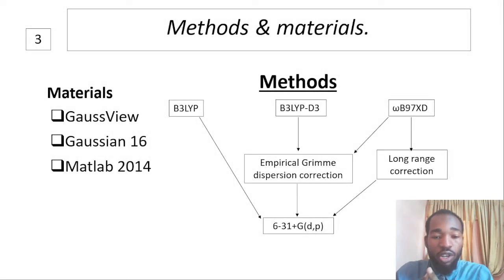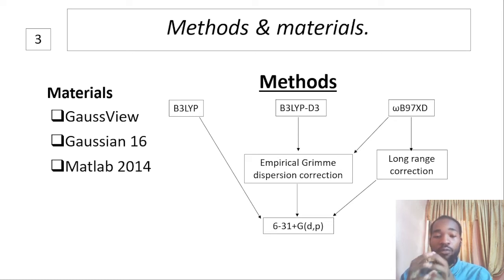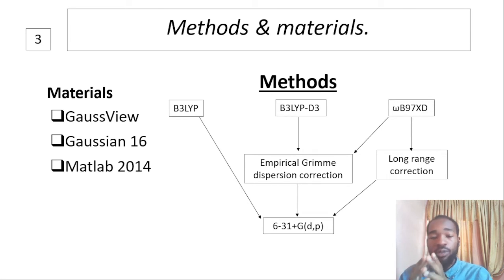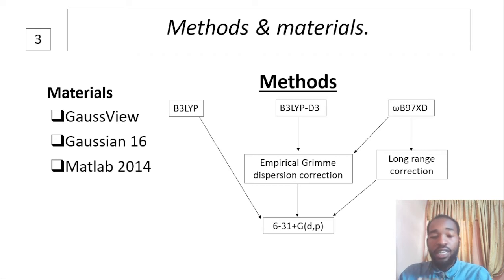In this work, we use the DFT method to study the properties of two compounds. All geometries were modeled in GaussView software. The DFT calculations were conducted using the high-performance computing facility of the CHPC in South Africa through Gaussian 16, using three hybrid functionals: B3LYP, B3LYP-D3, and ωB97XD, associated with a Pople basis set containing one diffuse function and two polarization functions.